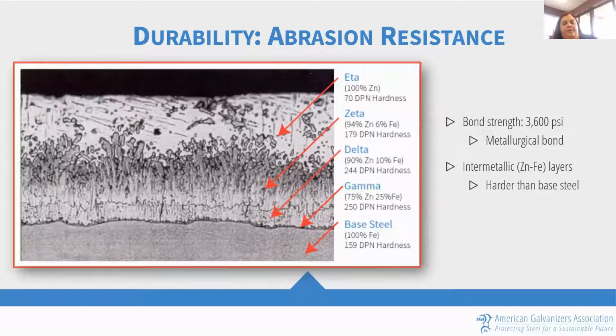Another benefit of hot dip galvanizing is its durability. And there's kind of a few different areas within durability that really come into play. The first is its abrasion resistance. And this has to do with the fact that the galvanized coating is not just a surface coating on top of the steel, but basically becomes a part of the steel and is intermeshed with the iron of the steel.